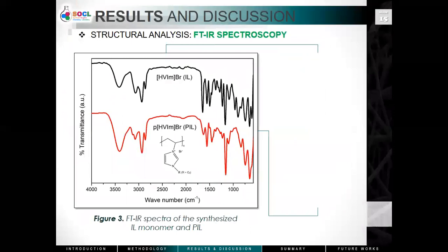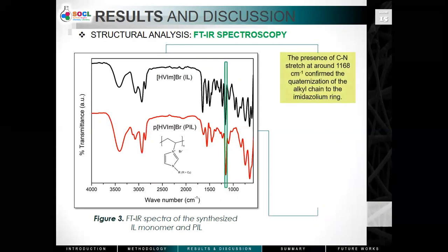The FTIR spectra of the synthesized IL monomer and PIL were obtained using attenuated total reflectance technique with transmittance mode. Looking at the FTIR spectrum of the ionic liquid, it can be observed that the C-N stretch was found, corresponding to the functional group present in the imidazolium ring. The presence of C-N stretch at around 1168 per centimeter confirmed the quaternization of the alkyl chain of the imidazolium ring.